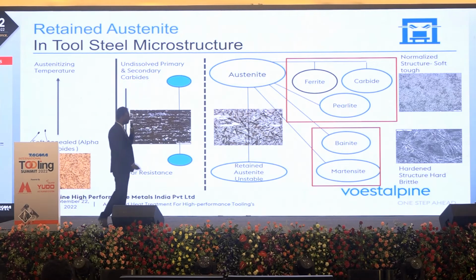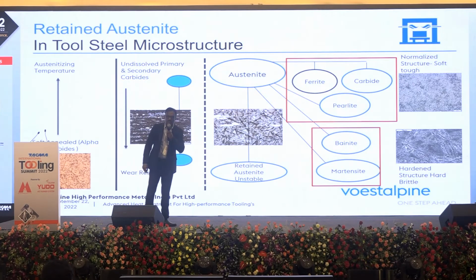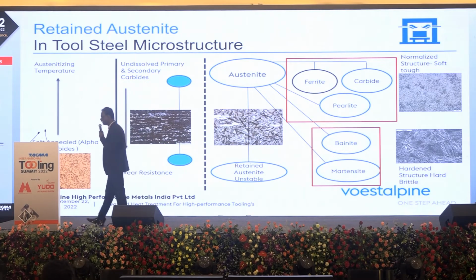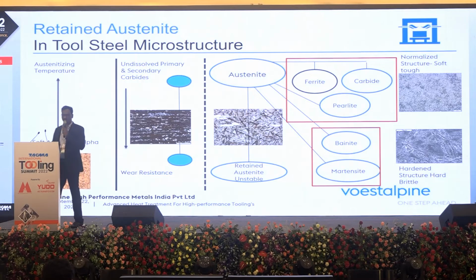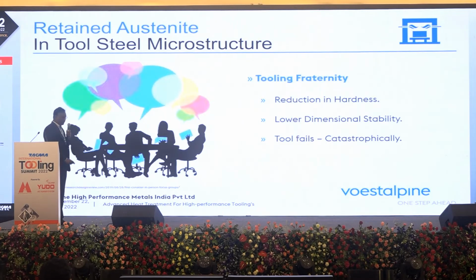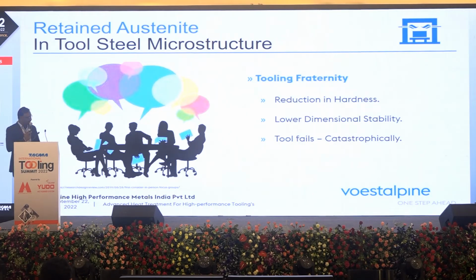The normalized structures could be softer. That can be useful for further mechanical working in steel mills, but may not be applicable for our tool steels. So what will the tooling fraternity think about retained austenite? They think there could be some reduction in hardness and lower dimensional stability if they want to do further value addition like PVD coatings. They think it may not be dimensionally stable, there will be expansion and contraction because of these detrimental phases inside the material, and that may lead to catastrophic failures.